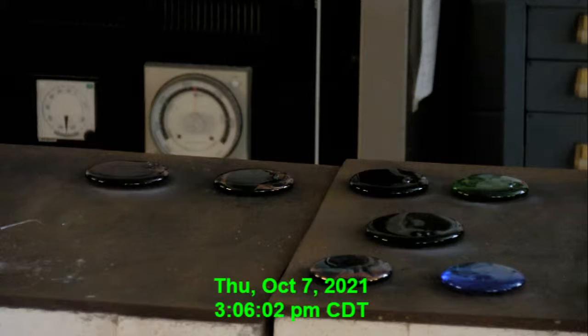This one, of course, cracked, and I put it back together so we can take a picture of it. Sodium is probably the most well-behaved. But potassium, which is even bigger, +1, is less effective. And so we end up with a much smaller piece of glass for a similar batch recipe. We're just substituting in lithium for sodium, potassium, and we're normalizing based on the amount of moles present, so 0.46 moles present of the flux. So these images will help you out in determining those relationships for the questions in the lab.